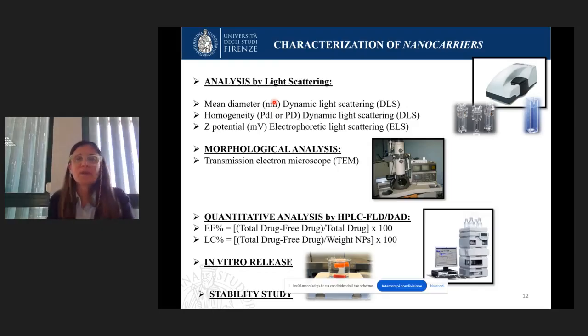Some words about the characterization of nanocarriers. When we prepare a nanocarrier, a nanoformulation, first of all we perform a physical characterization by dynamic light scattering or electrophoretic light scattering. With DLS, we define the mean diameter of the carrier. Then the nanocarrier is about 10, 20, 50 nanometers. The dimension is important for the route of administration. If we prepare a nanocarrier for parenteral administration, the dimension is around 200 nanometers. Also by DLS, it's possible to characterize the homogeneity of the samples by the polydispersity index.